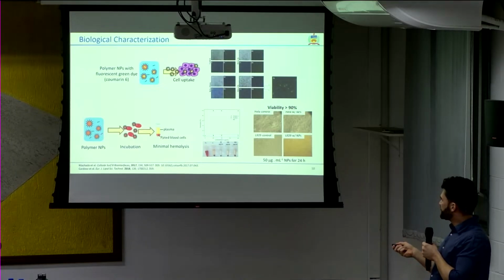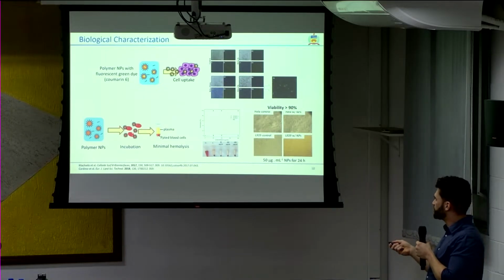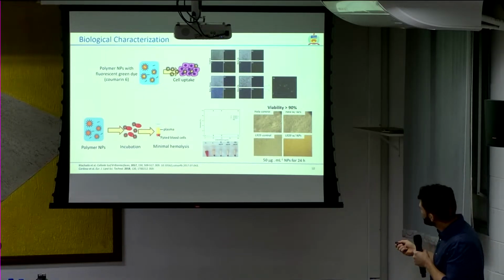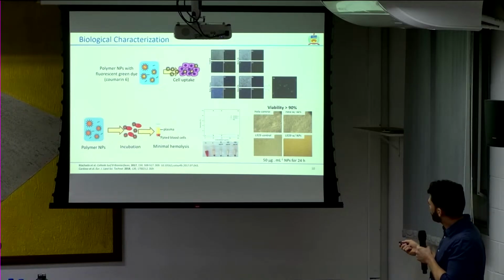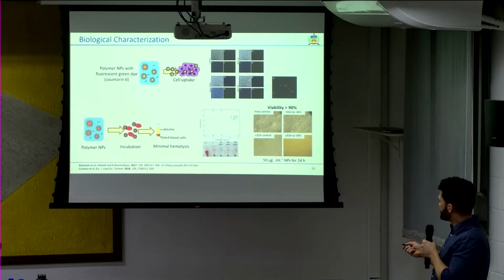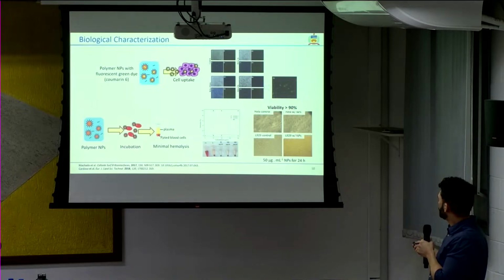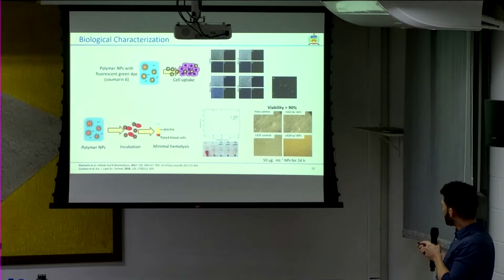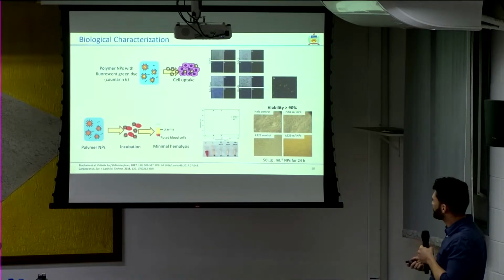And then we also studied the hemolysis to see if the blood was stable when incubated with the nanoparticles. Even at high concentrations of 200 micrograms per ml, we could see that the blood cells were not broken, because here the plasma is clean. If it was hemolytic, then the cells would break down and the plasma would be red. And also the viability of these nanoparticles was high, above 90% for 50 micrograms per ml. And these are the morphologies of the cells before and after the incubation.